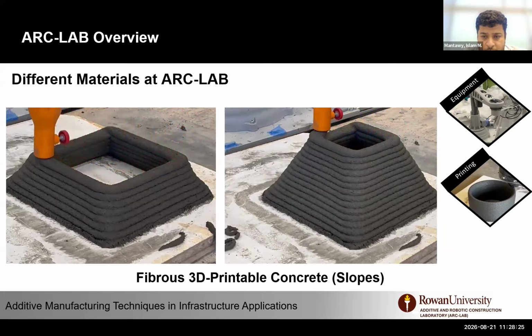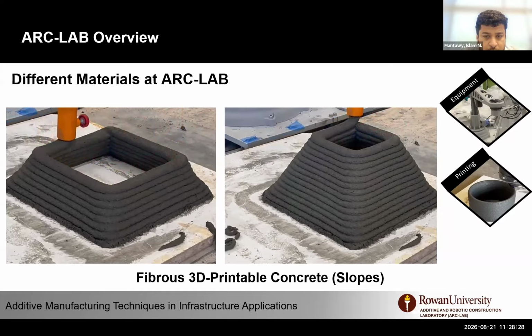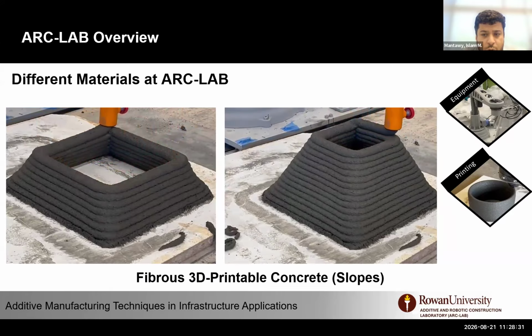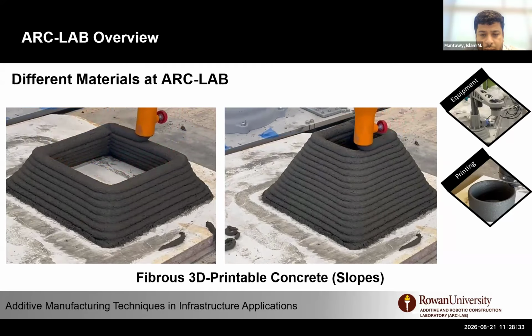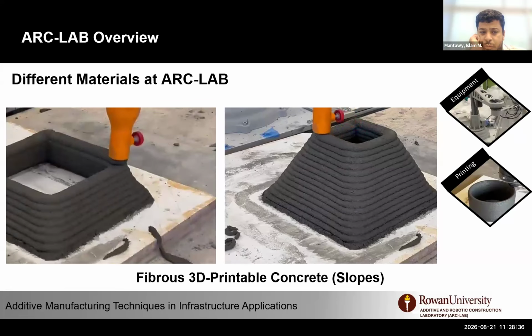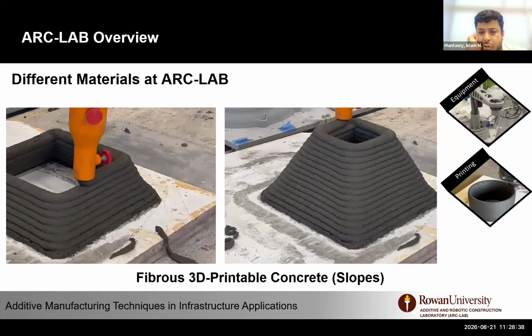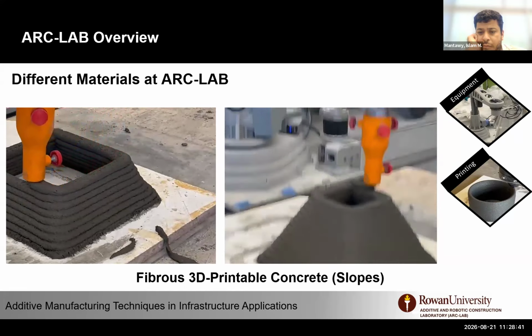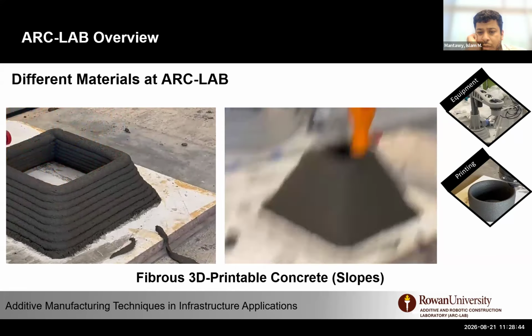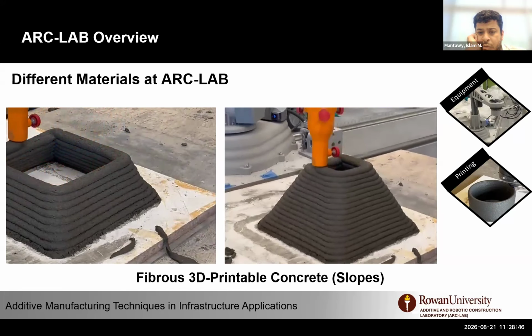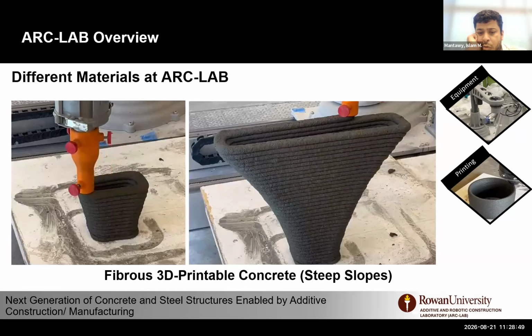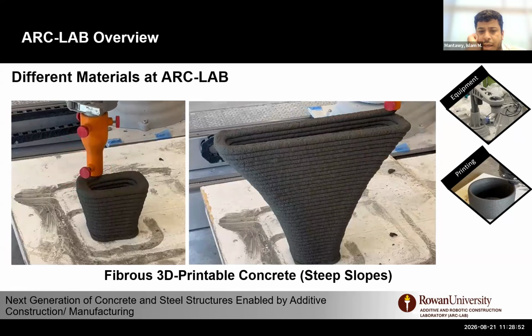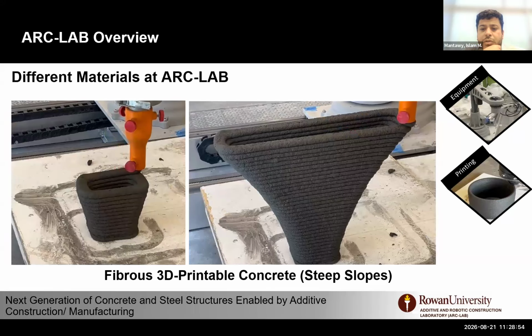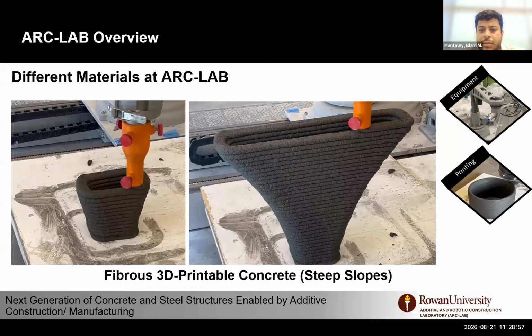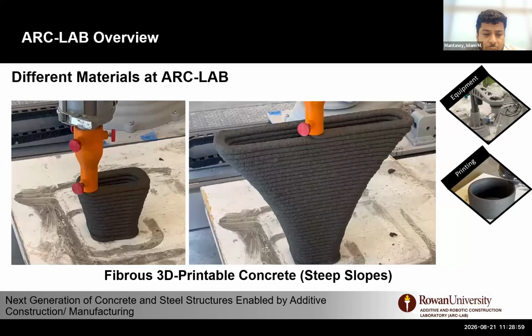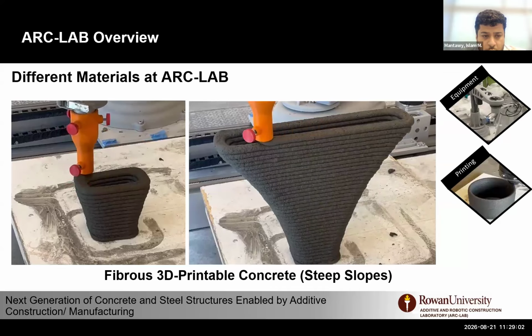So you can see here, we print this full pyramid without support using the fibrous mix we have, and also printed without fibers. And the idea here is, can we unleash the potential of 3D printing by printing on such slopes? So this slope is 26 degrees from the vertical position, and we're able to complete the entire structure. We also take it one further step and print a flare type structure, like a flared pier. So basically here, as you can see, with this same fibrous mix, we're able to print any slopes.